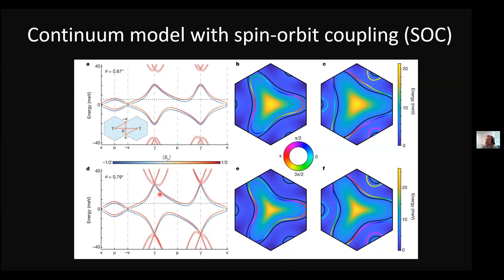So I should mention that this continuum model simulation you should take with a grain of salt. What we believe is that they work relatively well if you're far away from the magic angle, but at the magic angle they fail spectacularly. Here we are a little bit at the lower angle, so it might make sense to use them, at least for this case. But there should be caution when you're talking about relaxation and just this ratio.